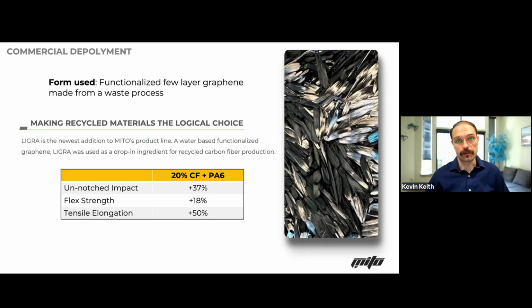Another commercial development that we've done is that we've taken a functionalized few layer graphene made from a waste process, so a bottoms up graphene. We did some extra chemistries with it, and we made a sizing solution that plugged directly into carbon fiber sizing for recycled carbon fiber, dispersed reactively. It's a water solution that's shelf stable. Right now we're up to 8 months.